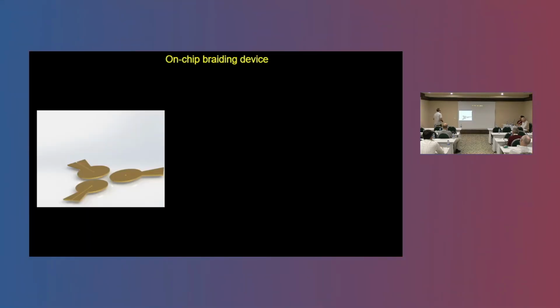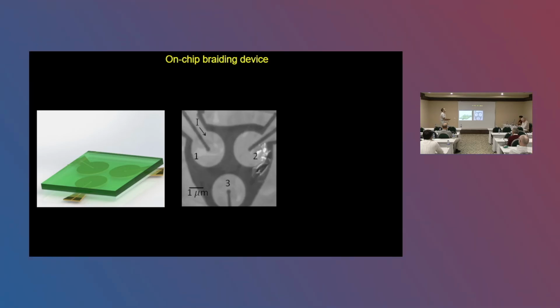So we call this an on-chip braiding device. So braiding vortices using scanning probes was done before, but the problem with this is that it requires to have the scanning probe. We're trying to do it just on-chip. So the way we do it is that we take 3 superconducting loops, we separate it with an insulator, and we put another superconductor on top. So this brown layer we call the control layer, and the green superconducting layer we call the target layer. And this is how it looks like looking from the top and the SEM.